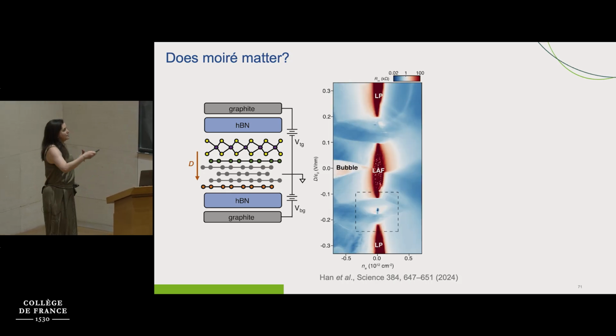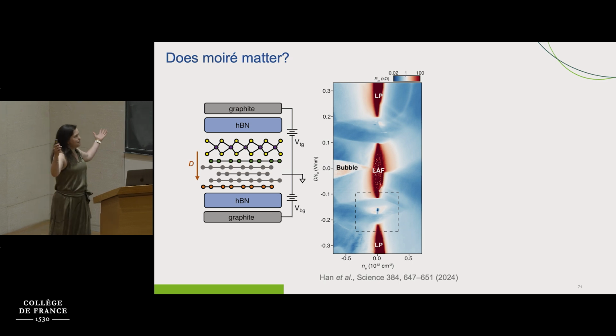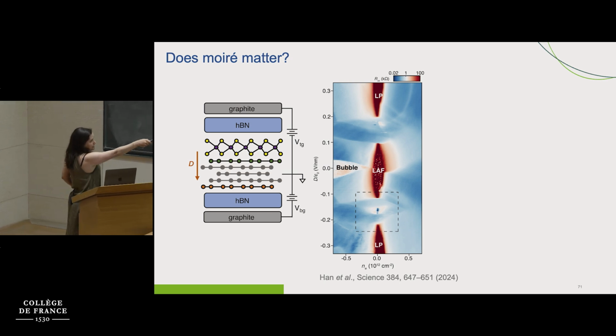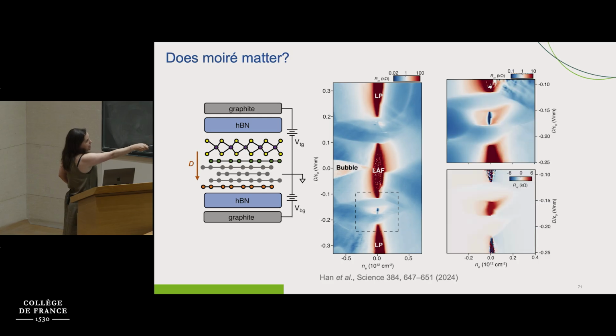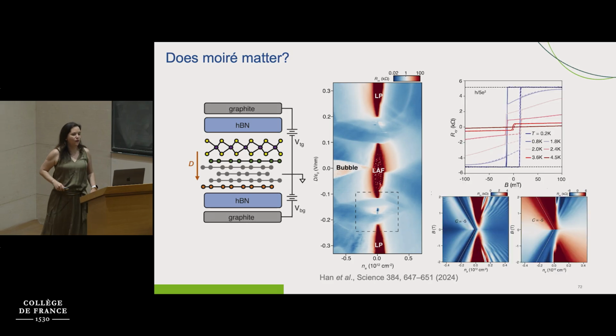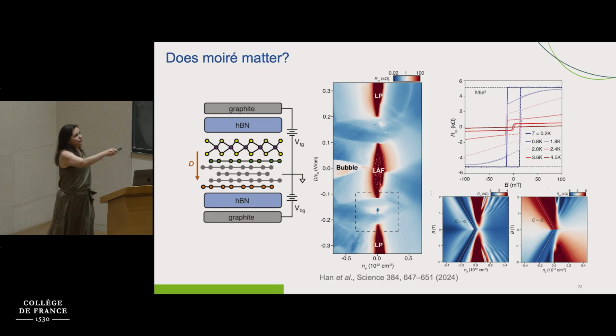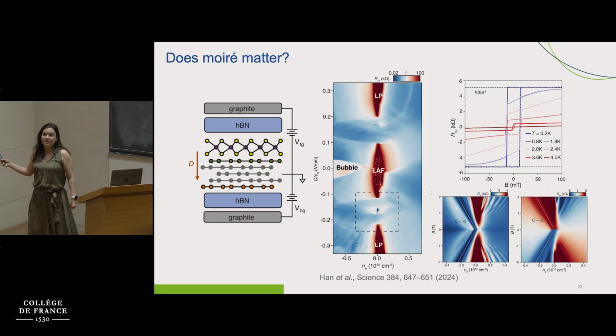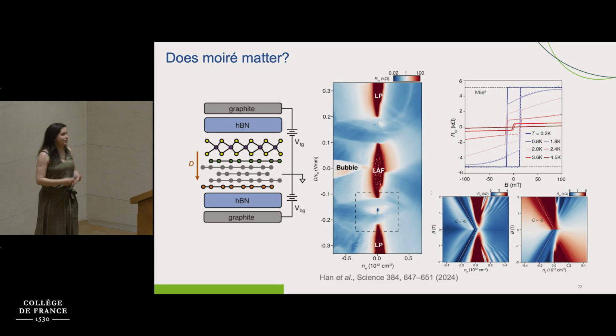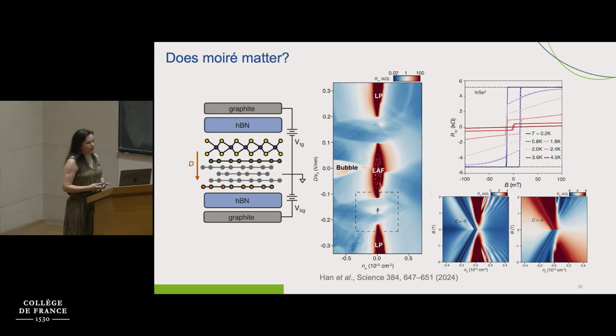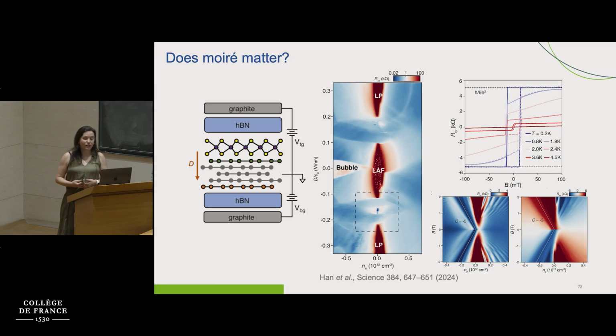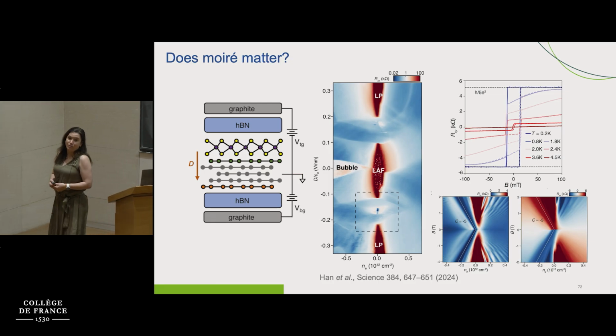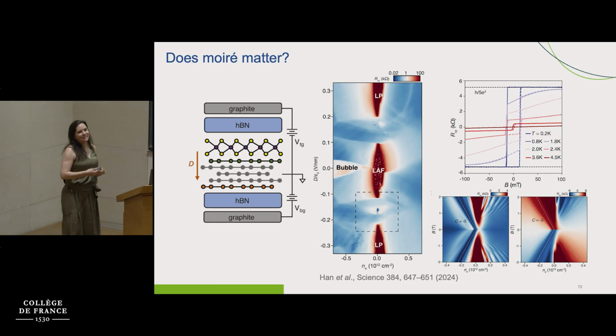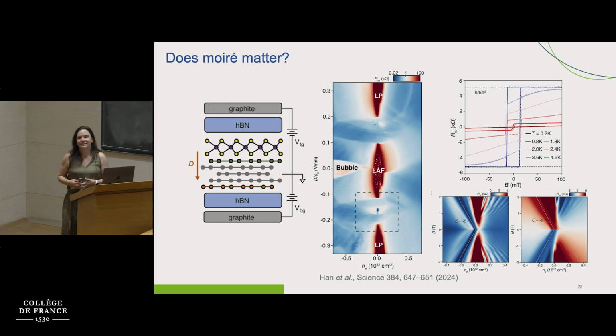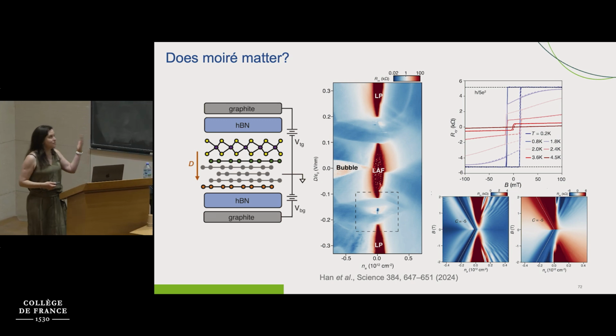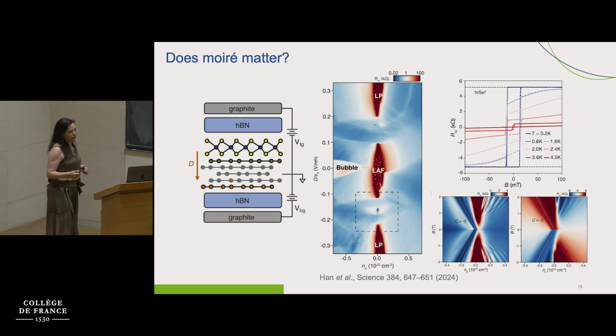So in fact, if you put these two in contact and make exactly the same measurements as you did before, you're going to observe in this little pocket anomalous quantum Hall effect, which is as clean as before. The difference is that the Chern number is higher now, but it's still a Chern number, it's still quantized, it's still the same physics. So, truth be told, Moiré might be important for Moiré materials, but Moiré is not the only way, and it's not a necessary condition to observe anomalous quantum Hall effect in rhombohedral graphene.